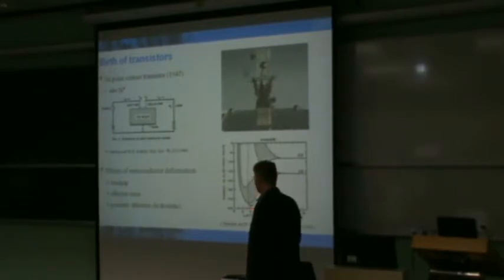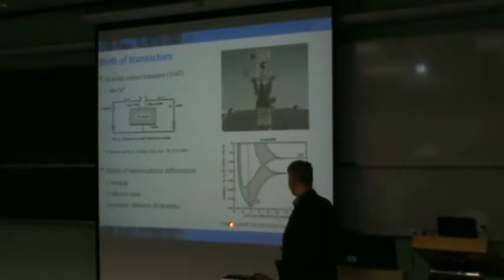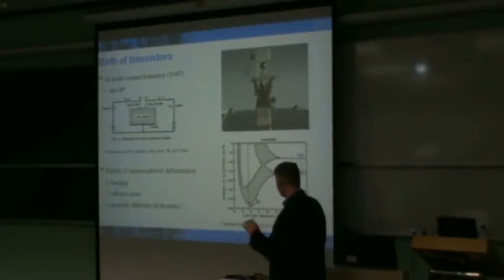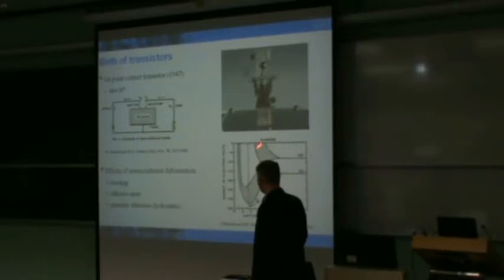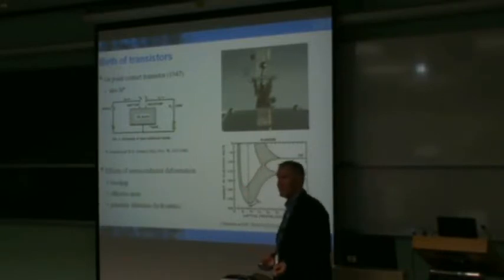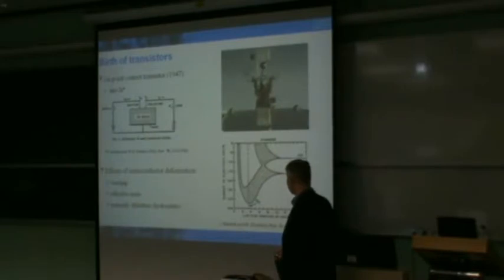And what I'm showing here is an image that was taken from Bardeen's paper in 1950, which first touched on these aspects. And clearly it's qualitative because it's a reference to another group 4 semiconductor. But it shows the fact that the atomic spacing clearly impacts the energy bands and the arrangements of them, to the point where if you get very far away, of course, then there's only one, or the quantum states are well-defined, and it's this incorporation of the lattice that actually causes the changes and the shifts within